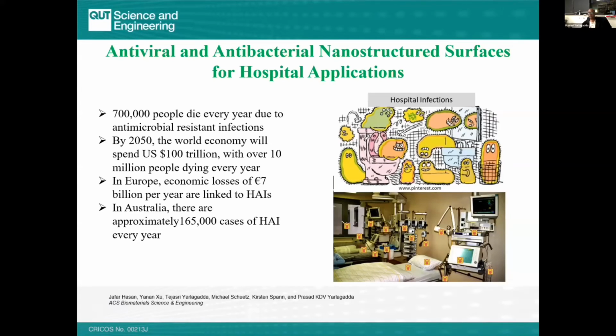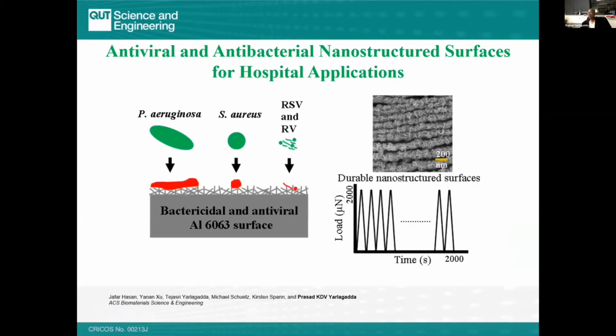Whereas with our nano-engineering approach, we tried 3 superbugs. We killed them within a span from 6 minutes to 3 hours. All the superbugs have also been killed by our surfaces. Hence, no problem of any antibiotic resistant bugs either.